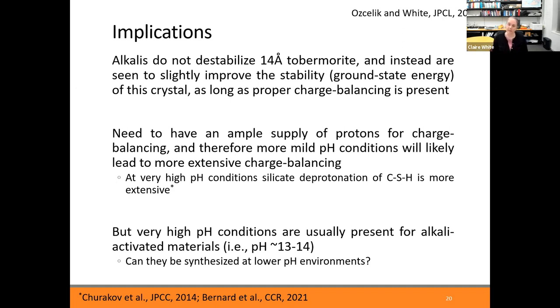What we're going to look at now is what happens if we are not just replacing one calcium with a sodium and a proton, but two or more calciums in the system. Because in the NASH gel that forms, there's going to be different amounts of sodium incorporated into the gel depending on how much sodium is in the vicinity when the gel's forming. That's an assumption that we have: if you have a low amount of sodium when the gel's forming, you only get a little bit of sodium ending up in the structure. Whereas if you have a much higher concentration of sodium during the formation of the gels, then it's more likely that a lot more sodium is going to end up in the phase, which could affect the performance of the gel.